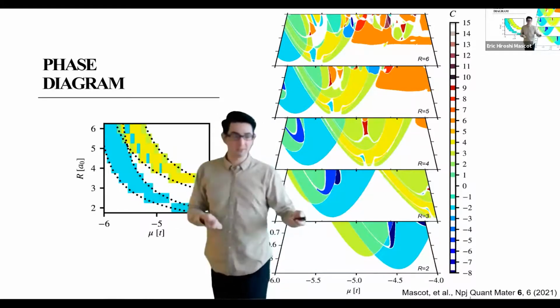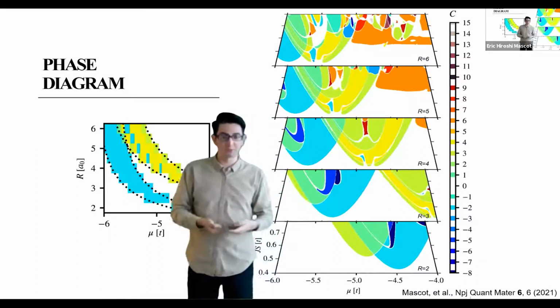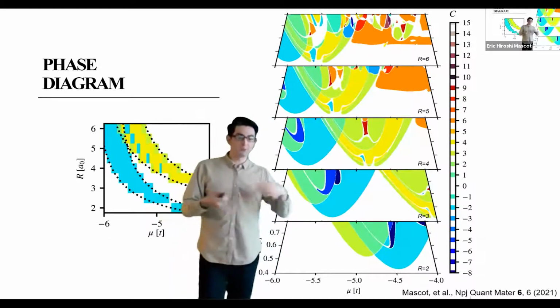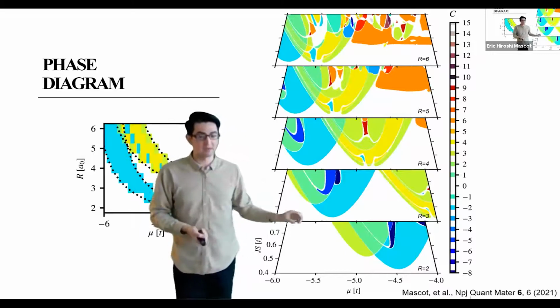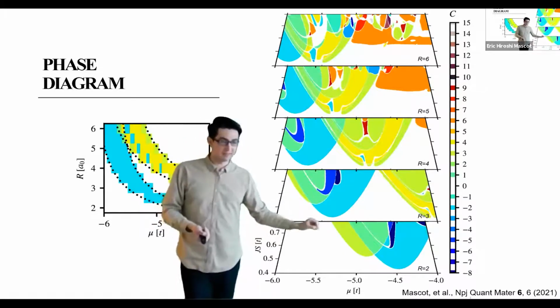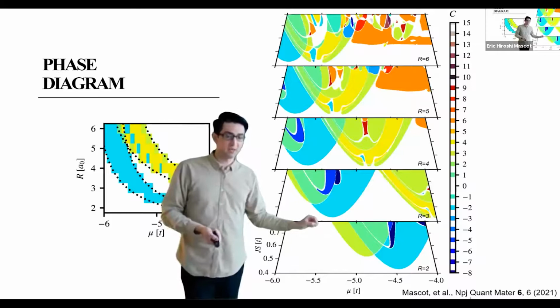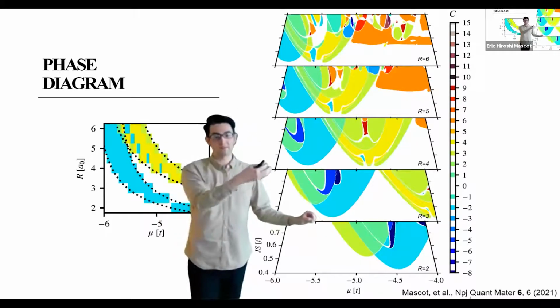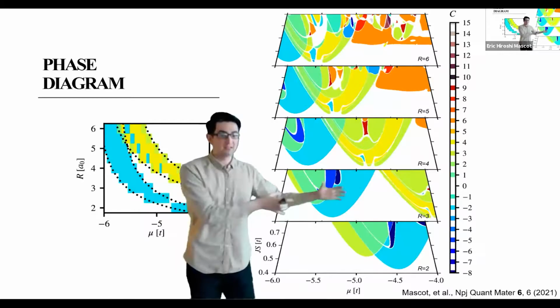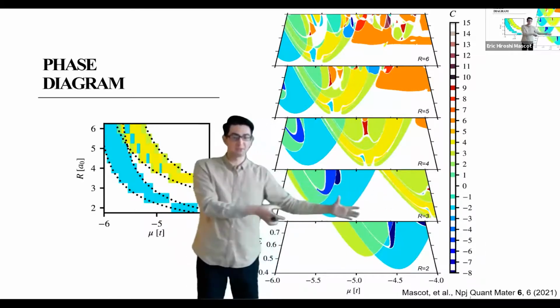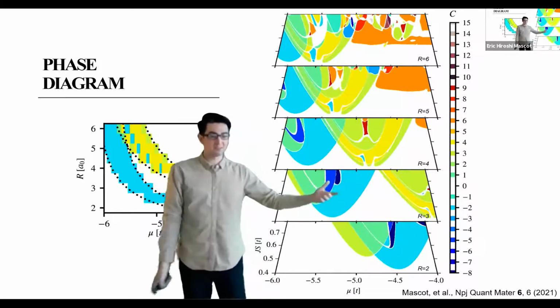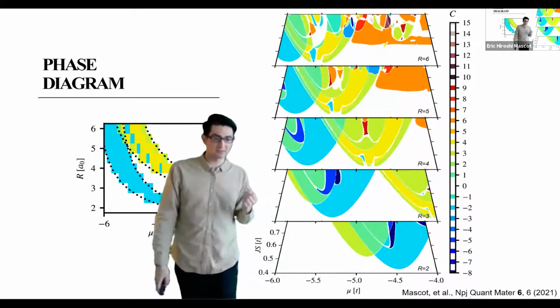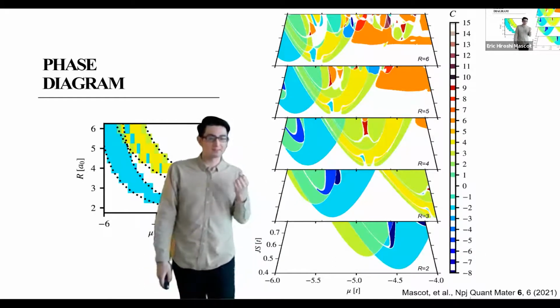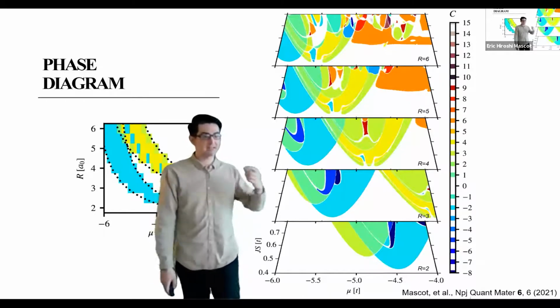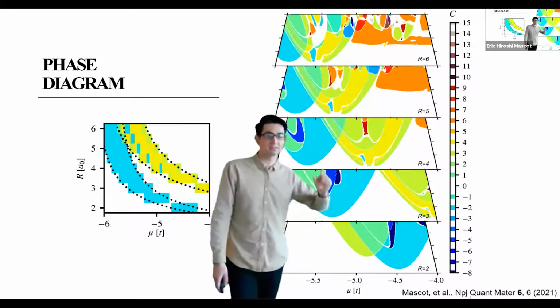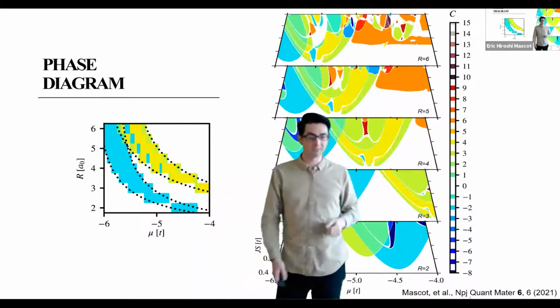So normally when you're fabricating these materials, growing them, you are pretty much throwing a dart randomly onto this phase diagram and hoping that it lands in a topological region. But now with the size of the skyrmion, what we can do is shift that topological region to that dart. And this can actually be done in an experiment because the size of the skyrmion can be controlled by an external magnetic field. So that gives us a tuning parameter that allows us to go between different topological phases.